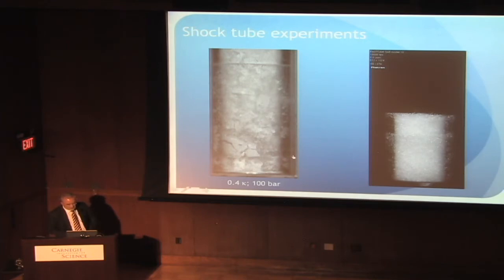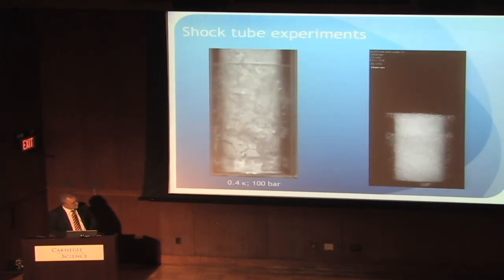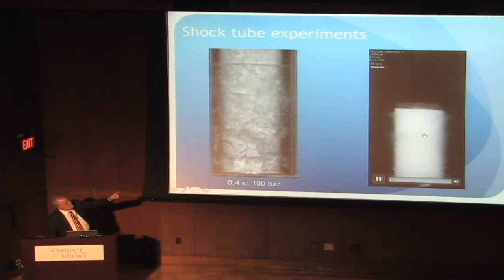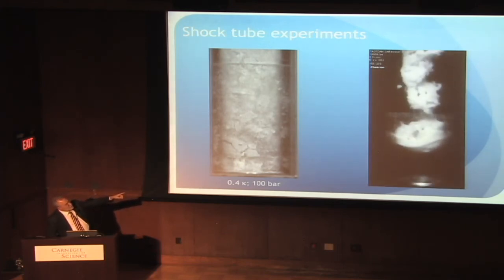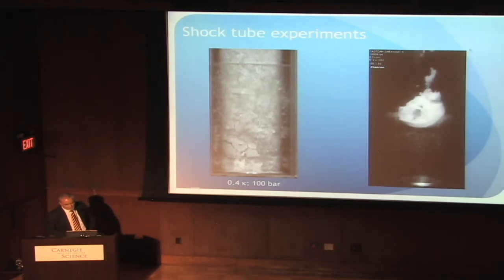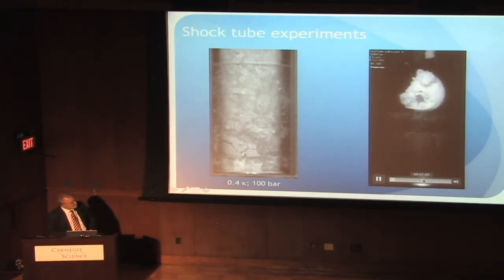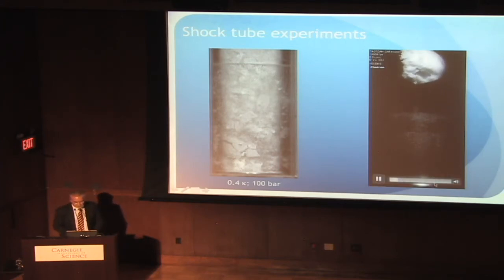If we look at the right-hand side, you see a sample where we allow a little bit of viscous deformation. It's not quite solid, and it's actually much closer to the case for most eruption of volcanic material. These are analog materials, but you can see, whoops, didn't want to do that. Try to get back, yep. You should be able to see here material which has some viscous response, see? But not enough to prevent it from ripping apart. Now this begins to look like products of basaltic eruptions, low viscosity eruptions, which have some deformation.